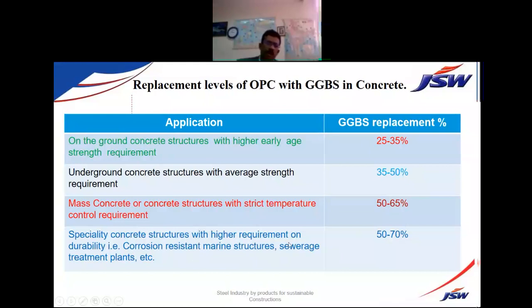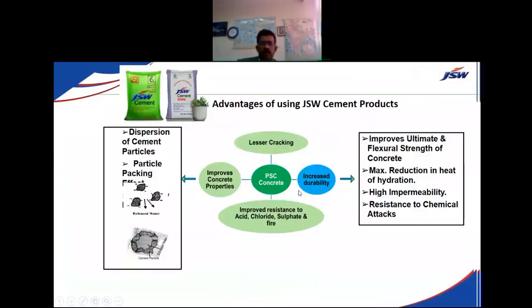And there are concrete structures built in the marine environment and sewage treatment plants, where 70% is a must because these structures come across sulfate attack, chloride attack, acid attack, alkali silica reactions. So the concrete has to be very strong. If you make it with 100% pure OPC cement, the concrete will deteriorate within 5 to 10 years. So to have a structure last more than 100 years, you need to go with a higher replacement of slag.